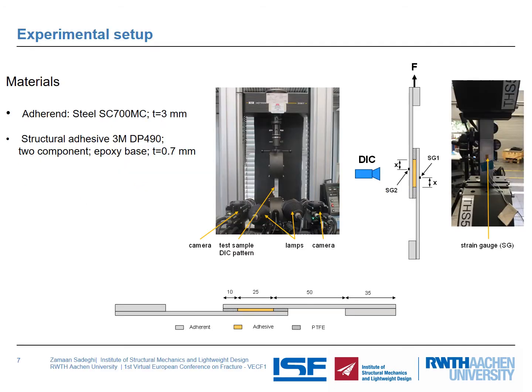The experimental setup is shown in the present slide, as you can see, and the geometry of the single lap joint is shown here. The material chosen for the adherent was steel SC700MC with a thickness of 3 mm, and a structural adhesive, 3M-DP490, which is basically a two-component epoxy-based adhesive with a thickness of 0.7 mm, was considered in the single lap joints tested here.